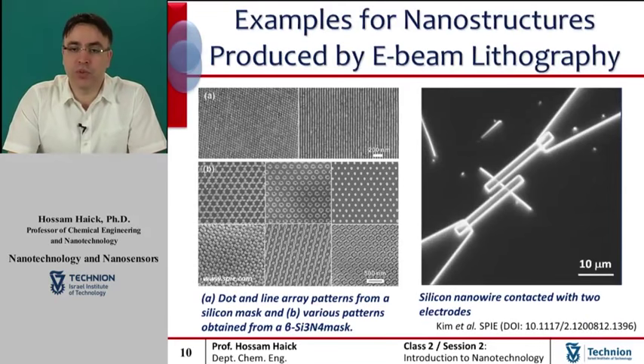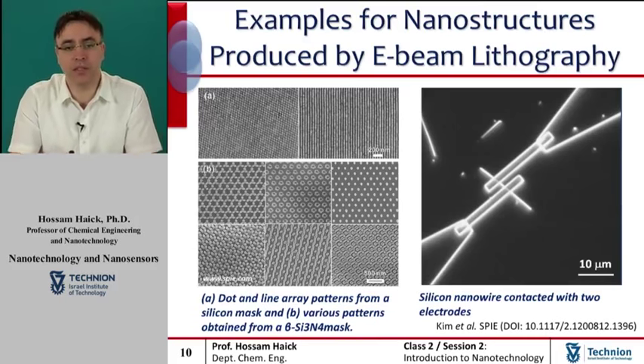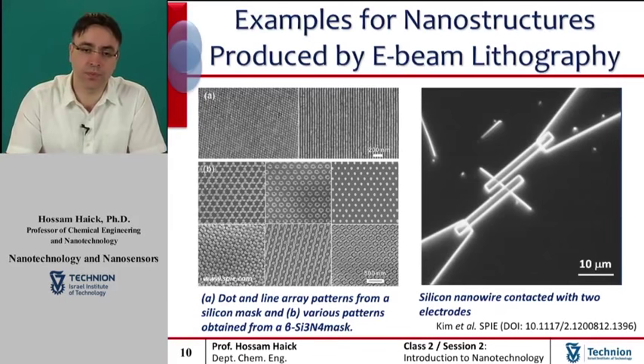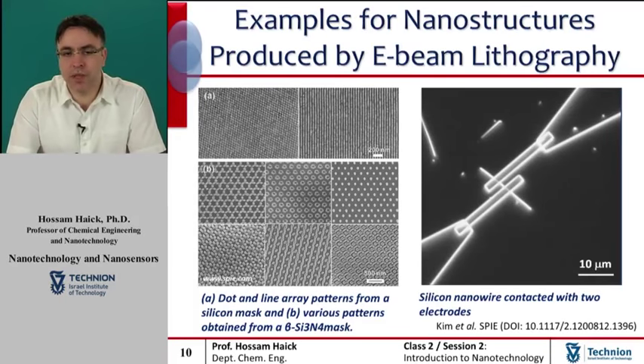The left side images demonstrate production level high-resolution electron beam lithography of lines and dots formed in a resist. In this example, 20 nanometer sized features were delivered and have a pattern transfer capability for a wide range of materials. Nanometer level-to-level alignment accuracy is made possible by the in-house software and marker design that is used in these systems and samples. The right side image includes a single silicon nanowire that is contacted by two adjacent electrodes to enable measuring the silicon nanowire's electrical properties.